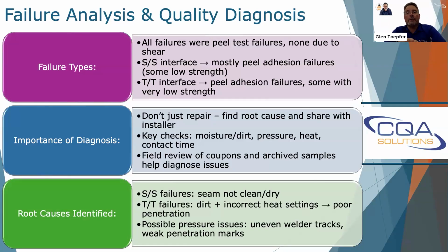I don't know. I'm not an engineer, but I'd see engineers that would say, okay, we had 25% peel, but we had our strength, so I'm going to pass it. And I've seen them, back when it was 4 or 5, they'd pass it with a spec of 80% of the strength. But where did it start to peel? A lot of times it starts to peel at a low pounds and it just gets up there. Sometimes it's even the squeeze out that gets the strength. So that's kind of another tangent there. I've got a lot of tangents I can go down, so I'll try and stay on track here for you.